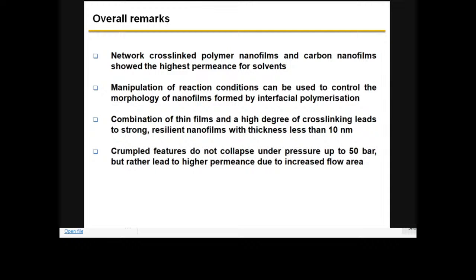So the overall remarks from this work: this network cross-linked polymer nanofilm and the carbon film that I just described in example one show the highest permeance of solvent. By manipulating the reaction conditions, controlling the interfacial polymerization, we can get different morphologies like a smooth nanofilm and a crumpled nanofilm. Combining this high degree of cross-linking, although it is very thin, a resilient nanofilm of less than 10 nanometers can be formed. Crumpled features don't collapse under very high pressure, as I just showed. It's also stable up to 50 bar, and we can get increasing solvent permeance under high pressure.